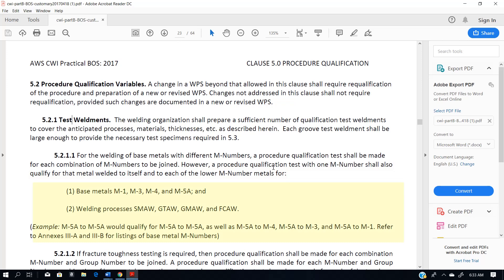The exception also includes base metal M5A, and the welding processes SMAW, GTAW, GMAW, and FCAW. So even though there are other M numbers listed in the annex, this exception that allows for welding of two different M numbers only applies to those specific M numbers.